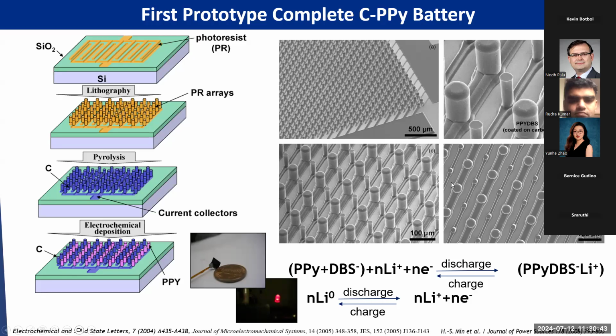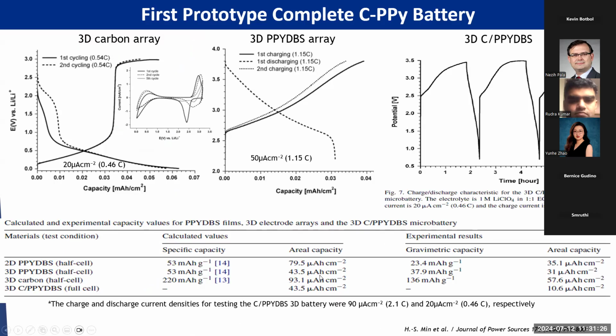And another thing is the leak current. So we can see when you do the carbonization, basically the carbonization process is degassing, then redeposit some of the carbon onto the silicon wafer. So in this case, we have the silicon oxide as the buffer layer between silicon and the photoresist layer. But after carbonization, there's always some residue redeposited on the silicon dioxide. Even if we try to do the plasma treatment cleaning, there's still leak current. So all these issues tell us this may be the main reasons for the poor performance of our first generation 3D batteries.